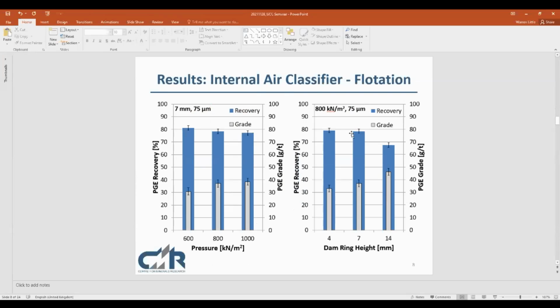Moving on to the flotation results, things don't necessarily agree with what we would expect, and it required a bit of thinking about the process. When we increased our grinding pressure, our recoveries actually dropped off. So for all the flotation tests that we had, grinding at a lower grinding pressure, say 600 kilonewtons per meter squared, produced a higher recovery of the PGEs and also base metal sulfides for that fact, than